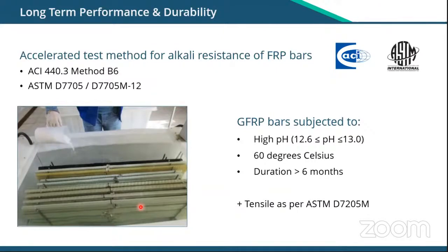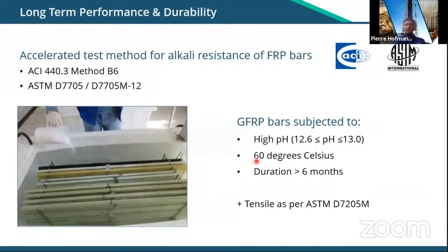So how to do this accelerated aging? We just push the pH to a very high level, between 12.6 and 13. And also we make the temperature very high, around 60 degrees Celsius. That means over a 6 months test, we can replicate again the ultimate time of 100 years or 120 years. And so the bars have been selected and taken after 1 month, 2 months, 3 months, 6 months, and we can see the impact over time.